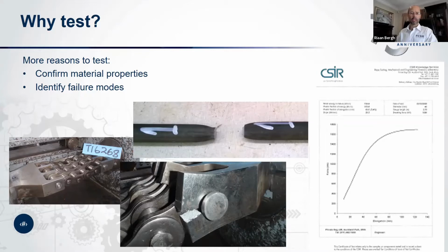So we designed the test fixtures that you see in the photograph, and the test fixtures design took into account the different failure modes that we were taught in university undergrad. And we realized pretty soon that the material had to be of quite a high tensile grade, because the chain elements are also of a similar high tensile grade. So within the size limitation of how you can attach to the chain, it prescribed that the material had to be of, if I recall, about an 800 megapascal yield strength, which the manufacturer of the test fixtures indicated would be no problem.